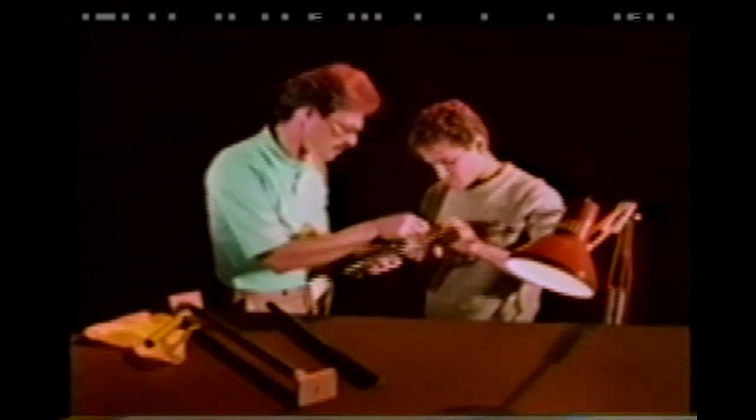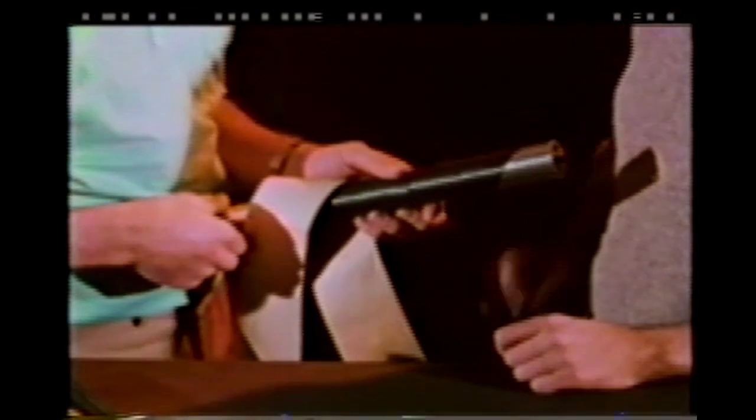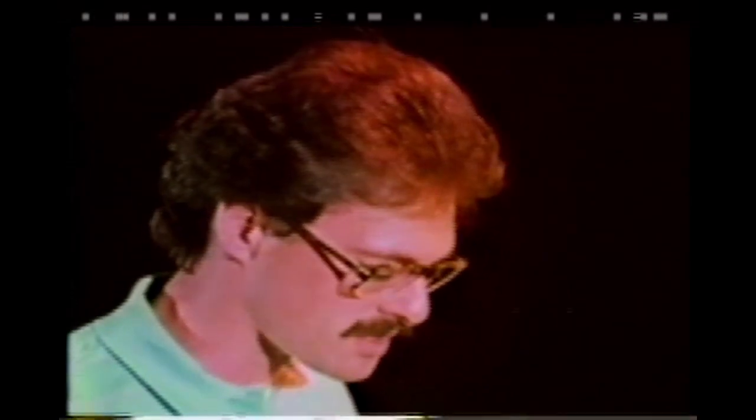The airplane is made from carbon fiber tubes just like this one, which have a very thin wall. To make it, we start with an aluminum tube and then take carbon fibers — which already have adhesive in them — and wrap them around the tube in a spiral down the whole length. When the tube is wrapped, you peel off the paper and that leaves the pure carbon fiber behind. That's your first layer of carbon fiber, and after that you add more layers depending on how strong you want the tube to be. The next stage is to bake the carbon fiber in an oven for an hour, which makes it very strong. Afterwards you pull the aluminum tube out and you're left with just a pure carbon fiber tube.